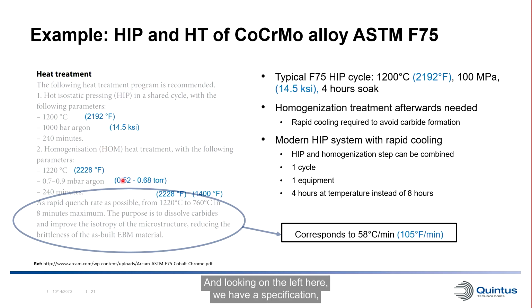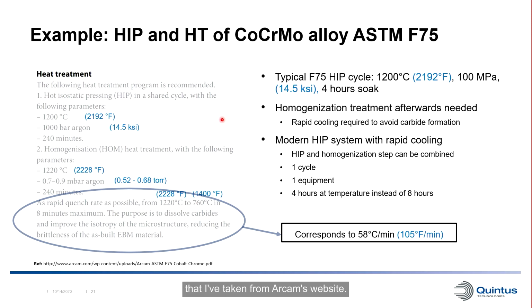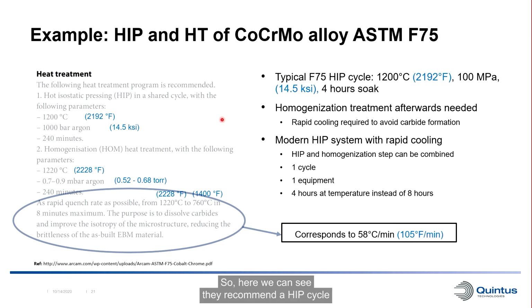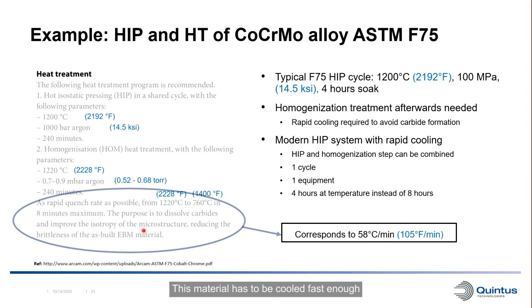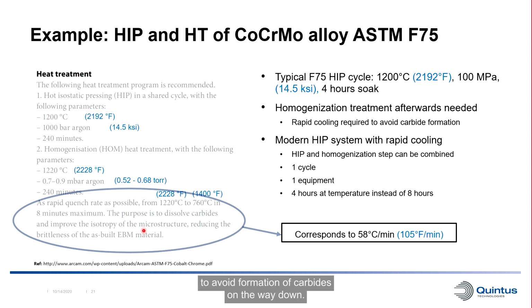And looking on the left here, we have a specification, which is a recommended post-processing route that I've taken from Arcam's website. So here we can see they recommend a HIP cycle first at 1200 Celsius, 100 megapascal for 4 hours. And then after this HIP treatment, they recommend a homogenization treatment at a similar temperature, 1220 Celsius, in vacuum, also 4-hour soak time. And the reason for this homogenization step after HIPping is that they have a requirement on a minimum cooling rate. This material has to be cooled fast enough to avoid formation of carbides on the way down. And this cooling rate corresponds to 58 Celsius per minute or 105 Fahrenheit per minute.